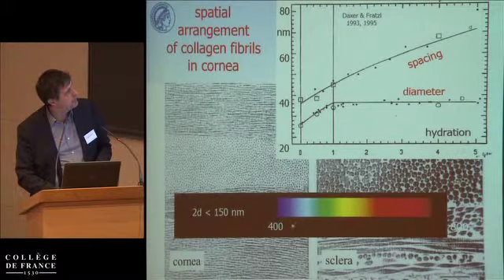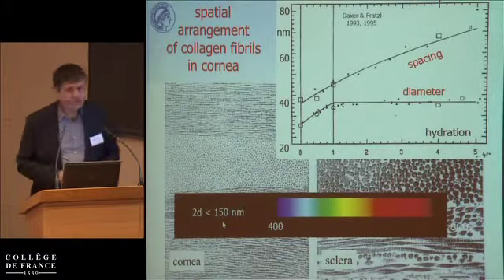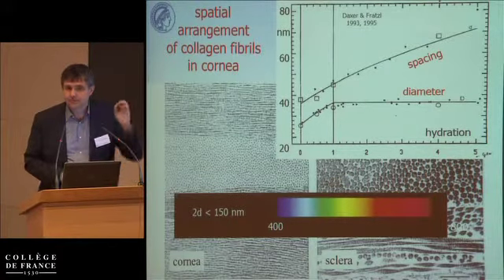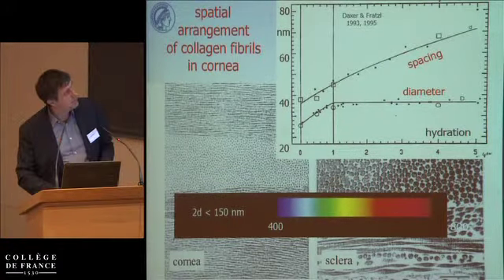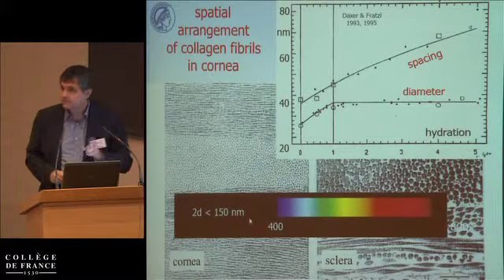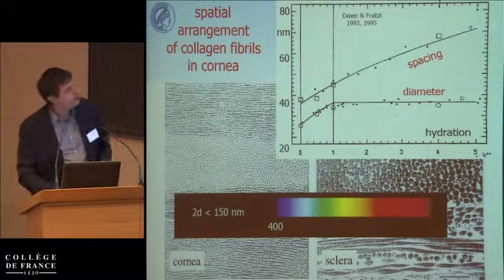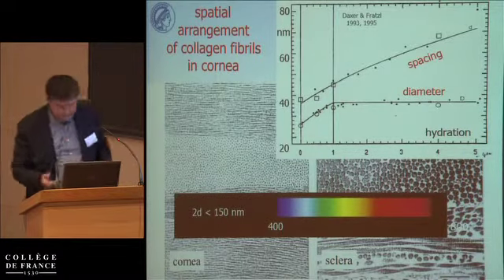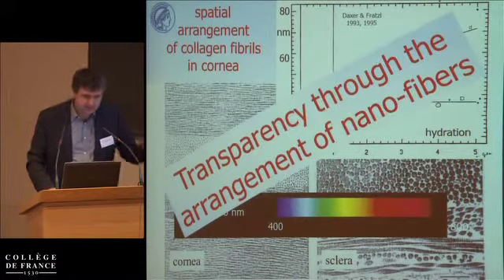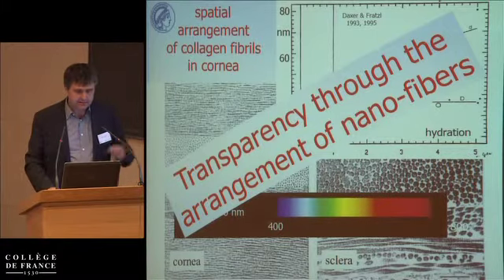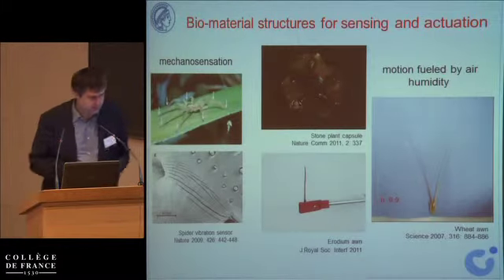So here is the typical range. So that's here 400 nanometers. And it turns out that 2D in the cornea is smaller, about 150 nanometers. So it's just such that visible light is not diffracted. But of course, ultraviolet light is, which is not a disadvantage. Yeah? And of course, in the sclera, everything's diffracted. So just to give you the idea that you can also manipulate light.